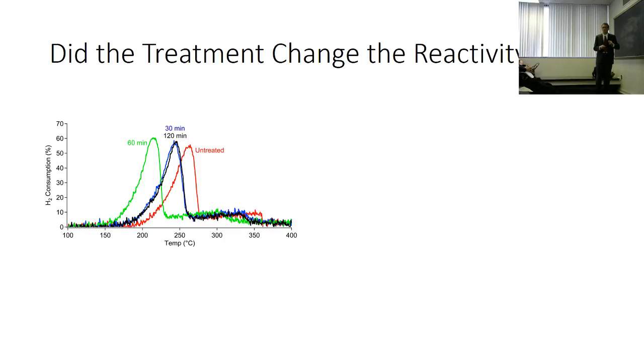As you go to the treatments, the 30-minute treated sample becomes more reactive. It reacts at a lower temperature. 60-minute reacts at a lower temperature. And then 120-minute, it comes back a little bit.